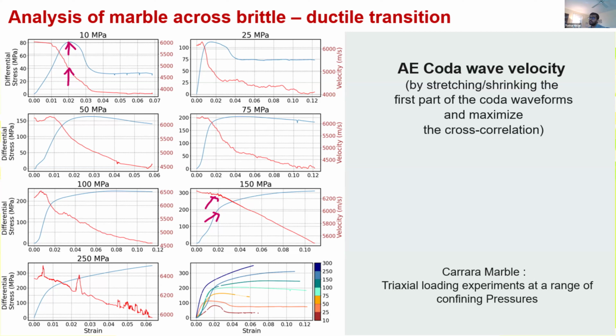So by looking at all of this, we can start to see, okay, within the context of a single experiment, yes, there are changes in the velocity that are potentially diagnostic of what the rheological state of the system is. But is this so if you just measured the velocity, right? Because our conjecture was that just by knowing the active waveform, you can tell what the rheological state of the sample is when you know nothing else. So if you just knew velocity, could you say whether you are ductile or brittle, for instance? So we wanted to test that.